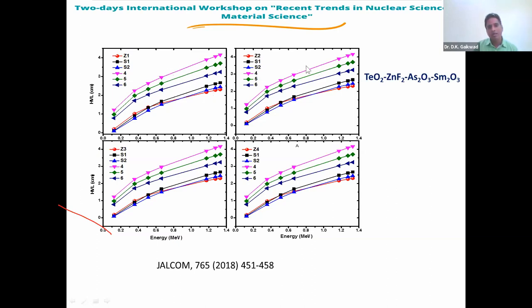Let's see, in all figures you can see the HVL of the glasses is lower than the concrete, and the HVL of these synthesized glasses is comparable with the other glasses S1 and S2. So we can say that the synthesized glasses have better shielding capability than the concretes, and are comparable with the shielding glasses.